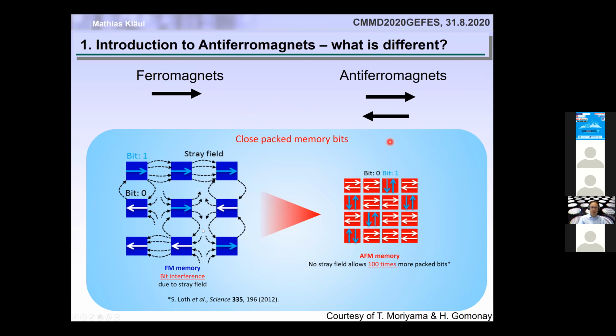If you have a ferromagnet, then in a ferromagnet, there is an interaction due to dipolar stray fields. So this bit here at the center has a different environment than this bit here at the center, because the two neighbors here are pointing in the same direction, and here they're pointing in the opposite direction. And that inherently reduces the stability due to bit interference.